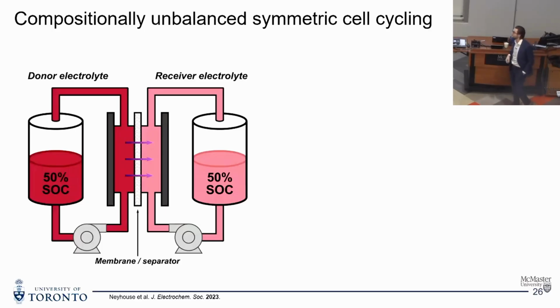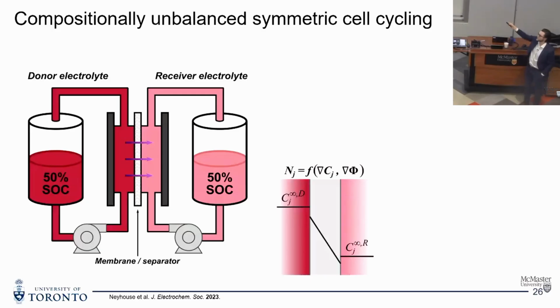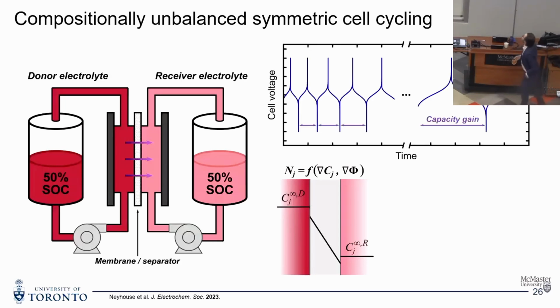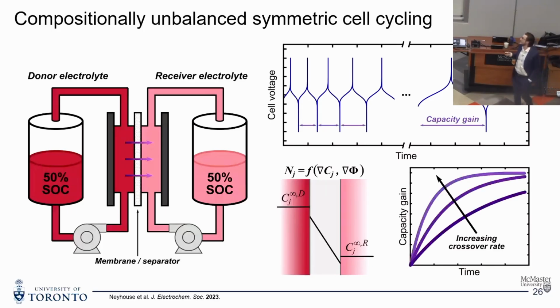Still a do-nothing cell. But if we have species moving over, and this is what we'll call our limiting electrolyte, then as species cross over into that electrolyte, we should see the capacity of that side increase over time. And so we tested this. Again, this is kind of showing the transport phenomena. We're looking at both concentration and potential gradients. And what we should expect to see is that the capacity is going to increase over time. And ideally, that capacity gain should tell us about the crossover rate.